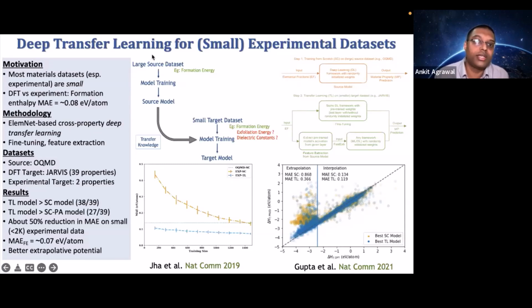So you have a large source data set, do model training, get a source model, and then for the small target data set, this source model can be reused in different ways to get the target models. One way is to do fine tuning: instead of random weights initialization, you use the trained ElemNet model as the initial model and then do the learning. Or you can do feature extraction. So from different layers of ElemNet, you can extract the activations and use them as the features for your target data set.